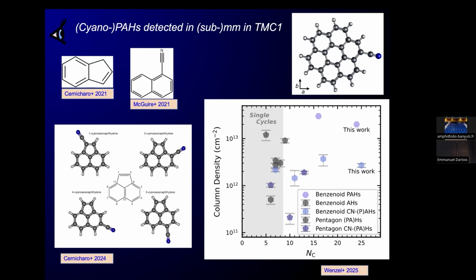And it has gone now up to coronene and maybe even higher than this. It has been detected in the Taurus Molecular Cloud. And the column densities you get are of the order of 10^12 to 10^13 per square centimeter, which is quite high for such a system, but still 10^-9 with respect to the column density you are probing. So they are really proven to be present.